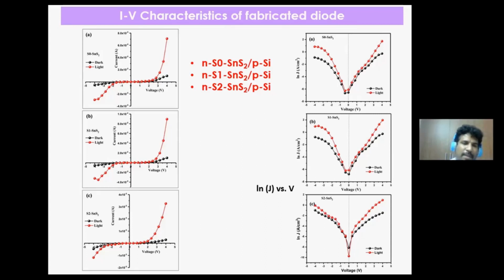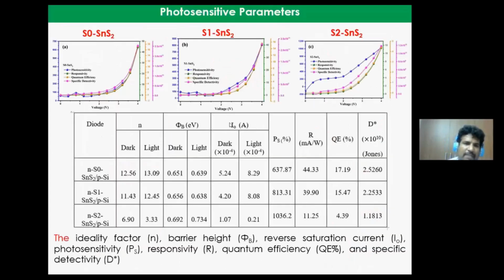Once the material is created and the IV characterization is checked, S1, SnS2 and S2, SnS2 show a beautiful difference in the IV characterization. With the IV characterization, we calculated the ideality factor, barrier height, reverse saturation current, and photosensitivity parameters such as responsivity, quantum efficiency, and specific detectivity.